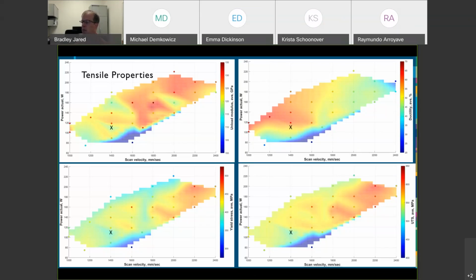Depending on where you want to be, we actually did some work where we were getting a ductility a little bit lower than the nominal we wanted. We showed that if we change our settings, we can actually increase the ductility of this material, maybe at a reduction of yield strength, but it was acceptable for that application. So really what this gives you is another design knob that says, hey, I can take my process or my geometry and tune the complexity of my part. In some ways, this is really exciting to the process folks and even possibly to the designer, because it gives you another level of control that may be useful.